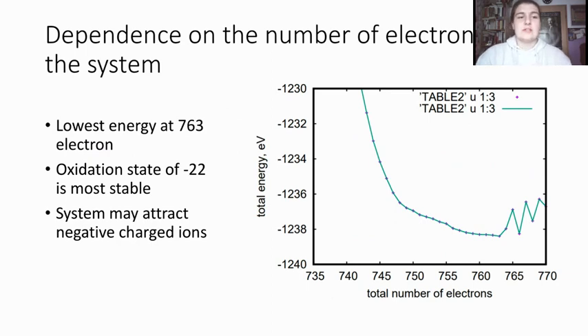Another observation is that when adding electrons to the system, the total energy decreases rapidly in the beginning and then slightly until reaching the minimum energy. And the model shows minimal energy at the oxidation state of minus 22. That means the model is most stable when 22 electrons are added to the system. And that means the system may attract negatively charged ions or electron donating molecules, for example, OH minus. And withdrawing electrons leads to an increase in total energy, so this is very unlikely to happen.